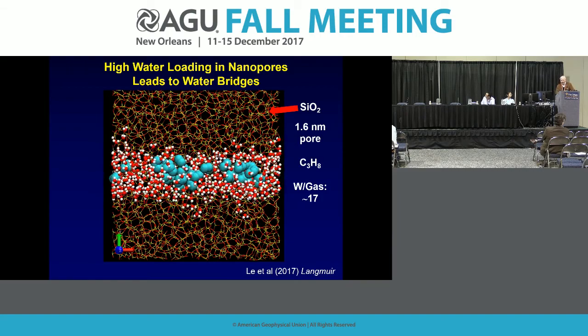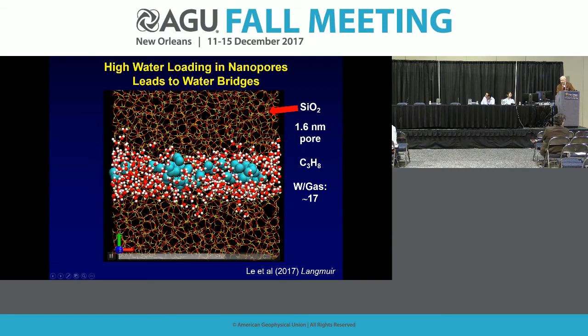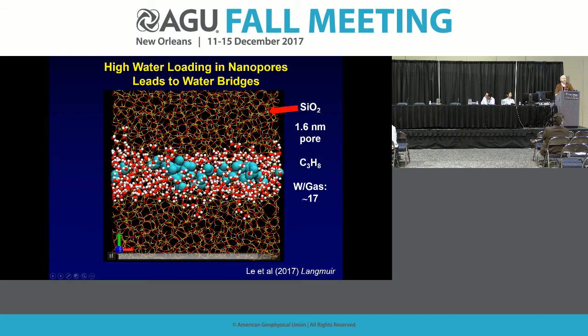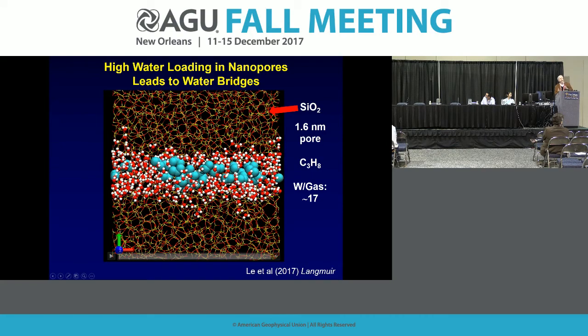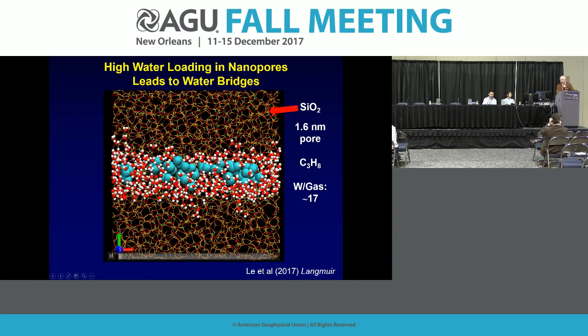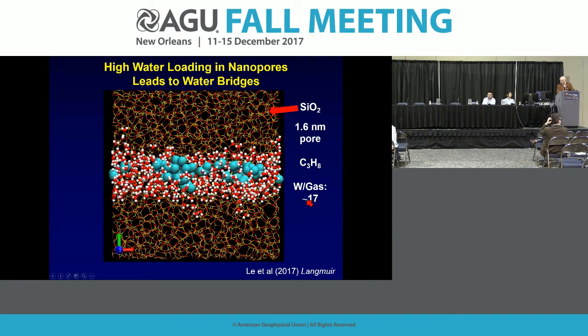And you can see these regions right in here. We get these water bridges that form across this pore, impeding the actual transport of propane, actually encapsulating that propane in this region here. This is at high water loading. We start changing that water to gas ratio, as we see in the next slide.